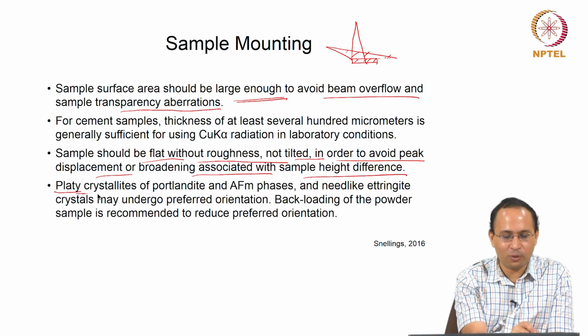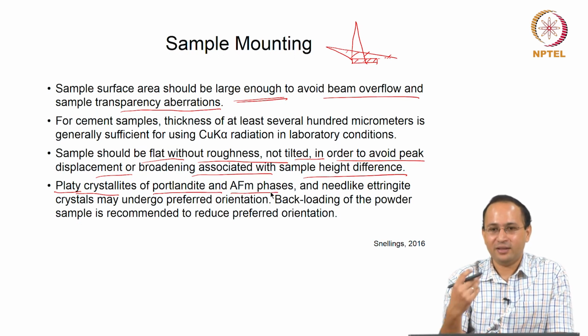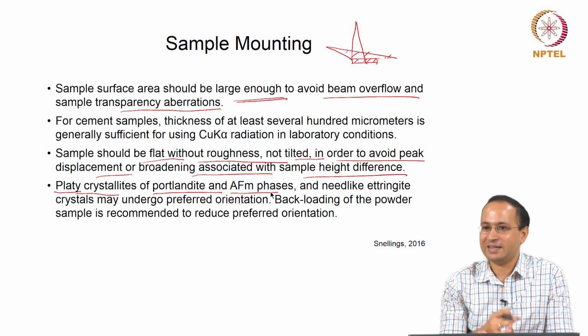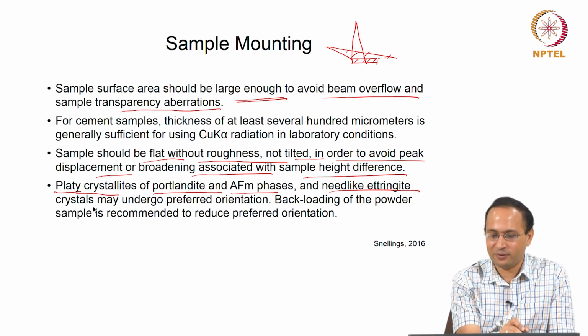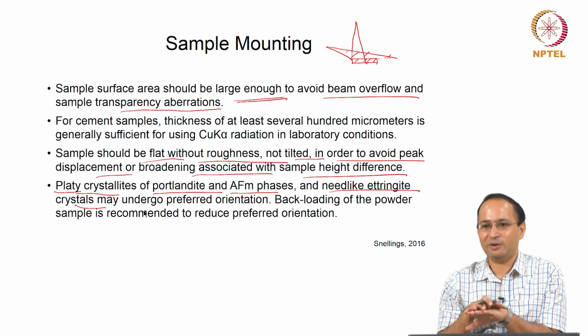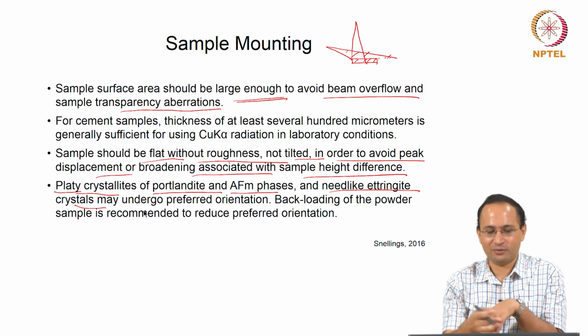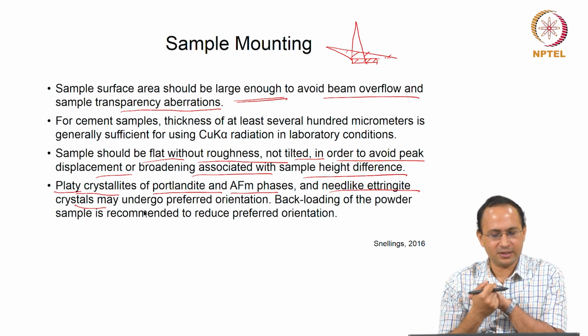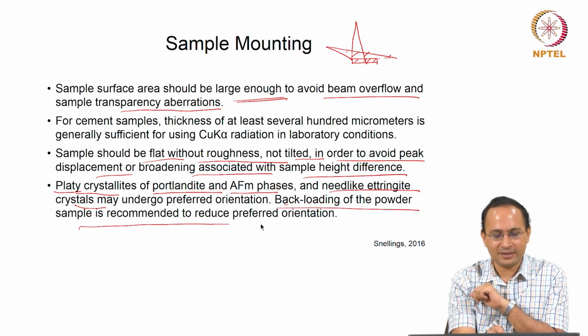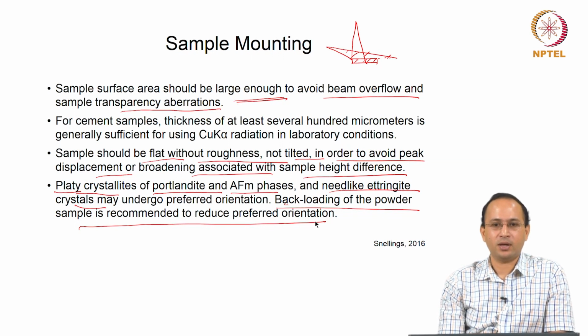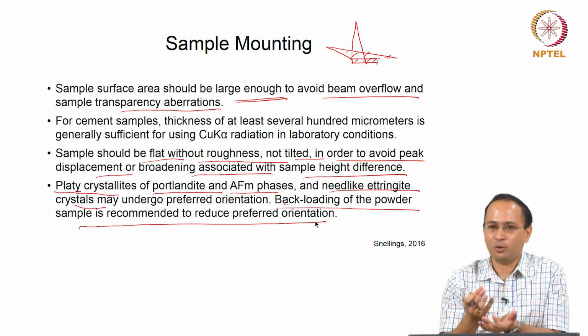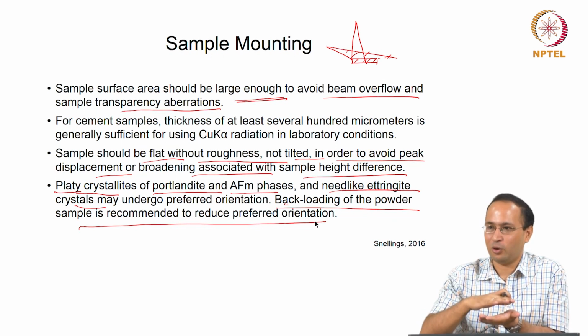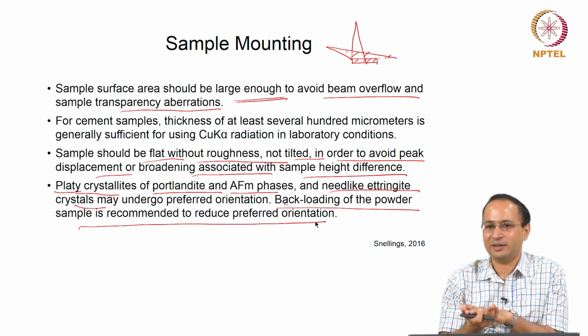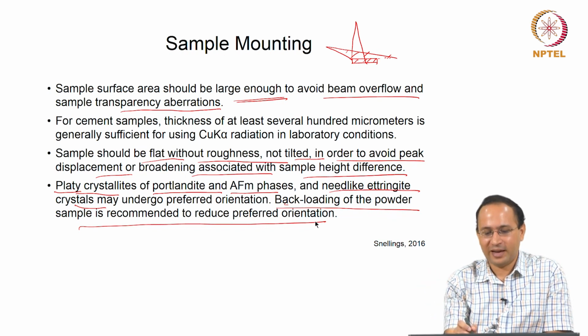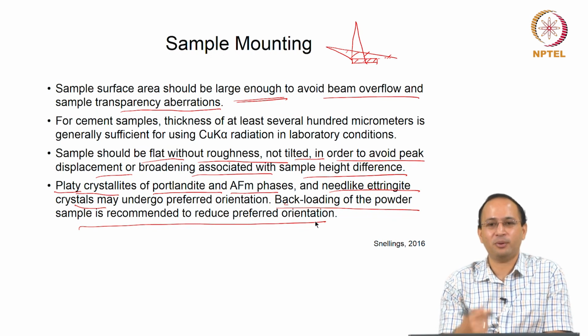Again re-emphasizing, very important: platy crystallites like Portlandite and AFm phases. These are phases commonly present in cement paste, and they have plate-like structures. Platy and needle-like structures, such as needle-like ettringite crystals, may undergo preferred orientation. They will tend to orient in a preferred direction just because of the nature of their shape. So, back-loading of the powder sample is recommended to reduce preferred orientation. Back-loading means, when you do powder diffraction, you have a sample holder, you put your powder in, and you press it. When you are pressing it from the top, you may lead to preferred orientation. So, back-loading means you are flipping your sample and then analyzing that part. That can help if you see preferred orientation in your sample.